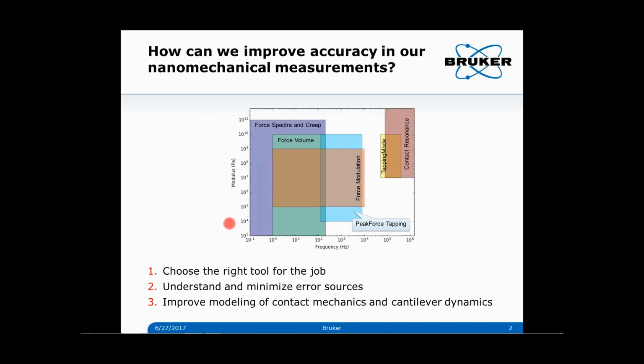The other thing is that the non-resonant modes allow a continuous variation of frequency, and since our moduli are a function of frequency, sometimes you would like to do the measurements at different frequencies, and this allows us to have more specific control over the frequencies at which we do the measurements. First thing, choose the right tool. Second, understand and minimize the error sources that are causing us a problem with the measurement. And then thirdly, improve the modeling of the contact mechanics and cantilever dynamics that are used to calculate these properties.